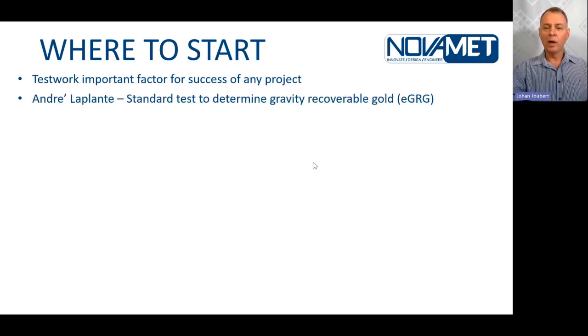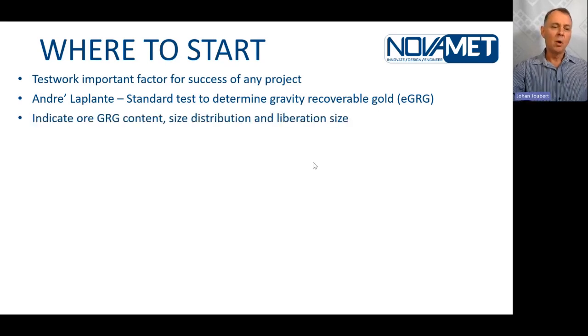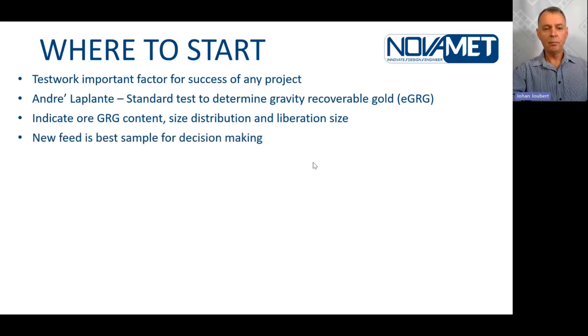André Laplante developed a well-proven standard test quite a while ago, which is still used throughout the industry today. This test has evolved a little bit and is now called the EGRG test, or the extended gravity test. What you get from this test is your ore content, your size by liberation, and also all this information is required if you want to continue further on with modeling or simulation in your project. We'll discuss this a little bit more in detail later.